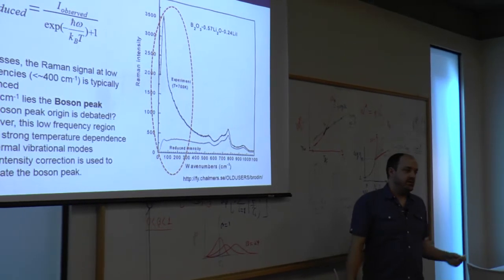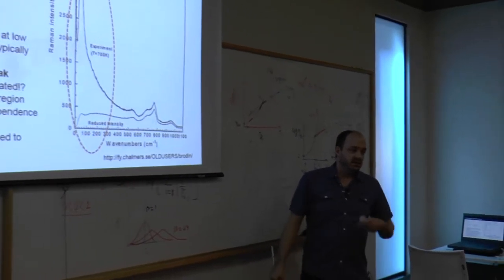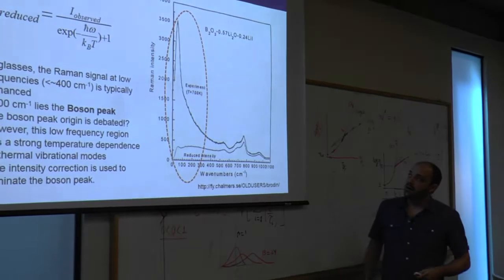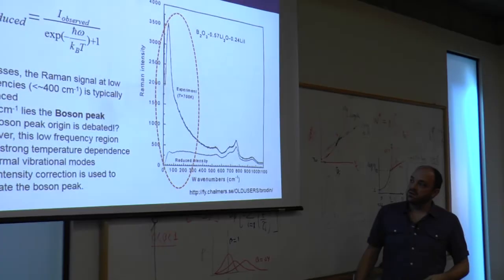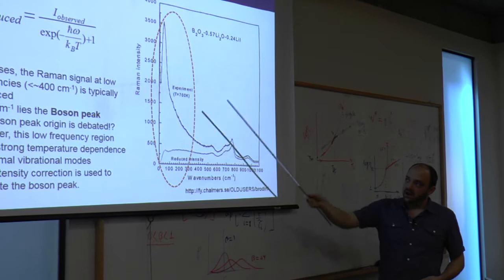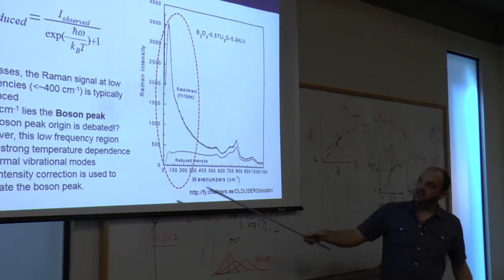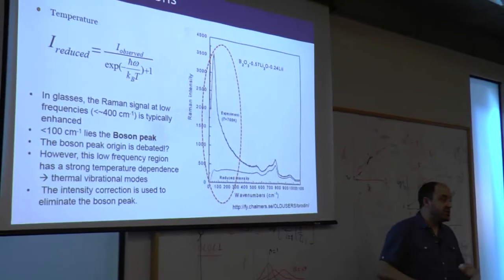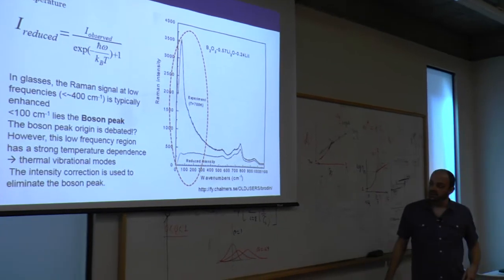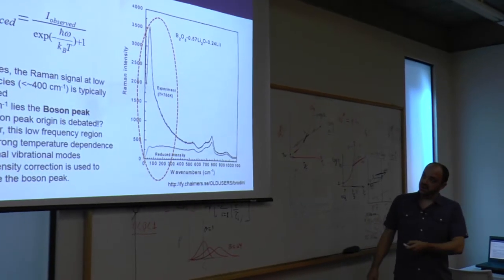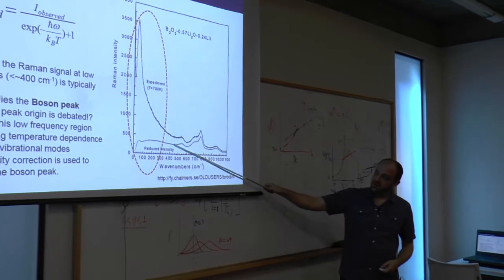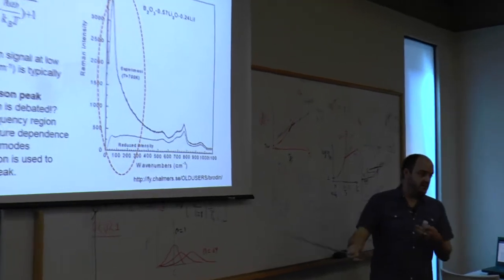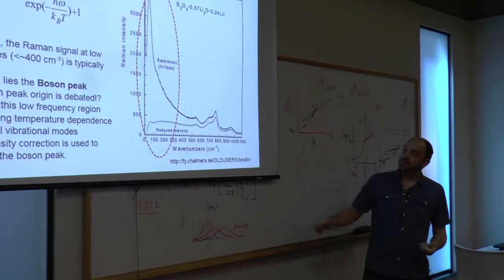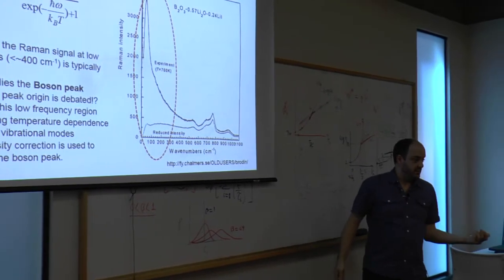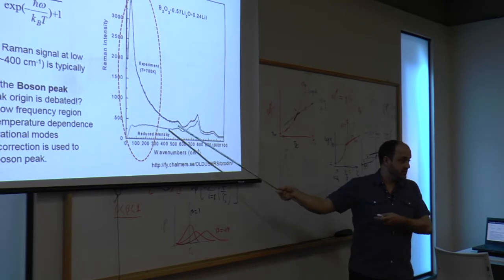And it was so popular, everybody still uses it, but now that we know it's a real thing and we can take some stabs at modeling what's going on with this peak, it may or may not be so applicable. I mention it because a lot of people just do it by default because so many people in the literature have used it. So just to highlight that sometimes the spectra is corrected, sometimes it's not. And if you want to compare spectra, you have to treat it in the same way. So if what you're trying to compare has been corrected, then you should probably correct yours. Or maybe try to do it with the correction, without the correction.